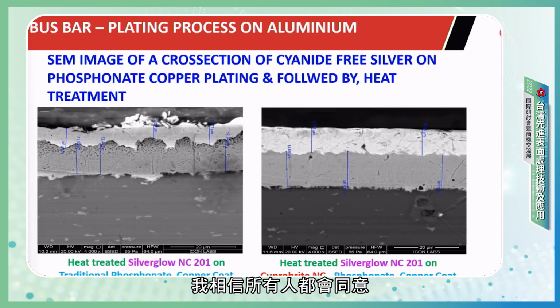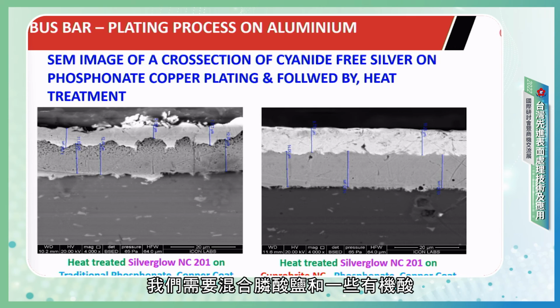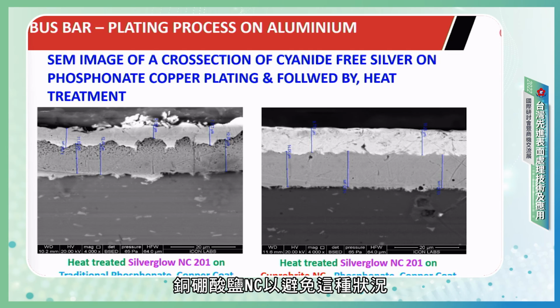I'm sure all of us will agree that if the coating deposition is lower by chance, and that component subsequently goes for heat treatment, there is a possibility that wrapping can take place on the upper layer of the deposited copper, and sometimes it can even touch the base material, and the coating fails. But with the Silverglow NC, with the mixed phosphonates and some organic acids, such situation will not occur.